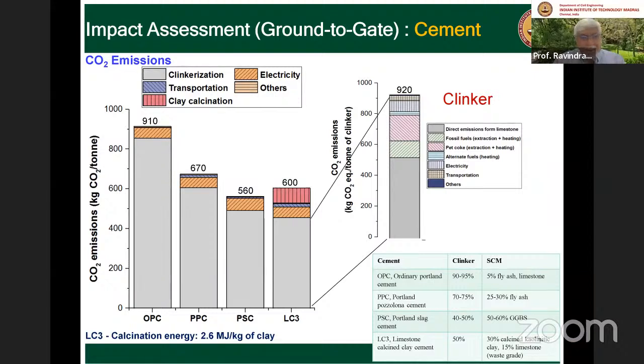So here I have compared the ordinary Portland cement. This is the ground to gate calculation. Okay, previously I had shown just what is happening in the plant. This is the ground to gate calculation of cement. 910 kgs of CO2 is associated with the production of ordinary Portland cement. Most of it is coming from the clinker. You see on the right, I have the breakup for clinker. 920 kgs of CO2 for every ton of clinker is what we are emitting.